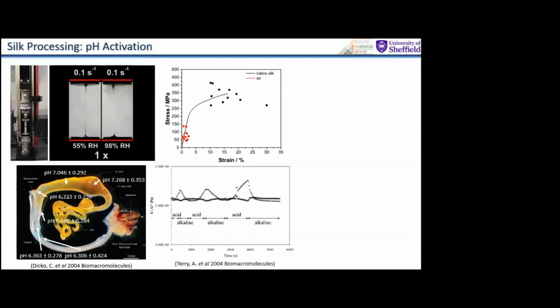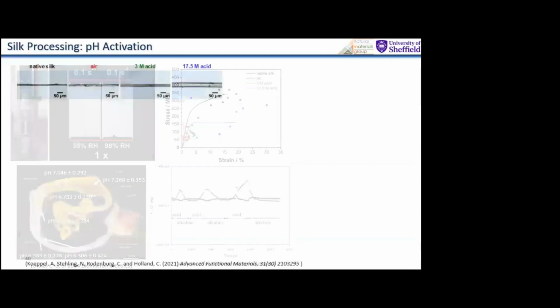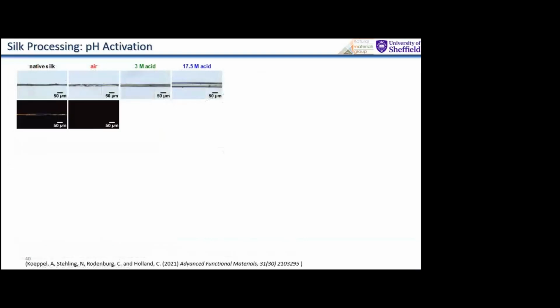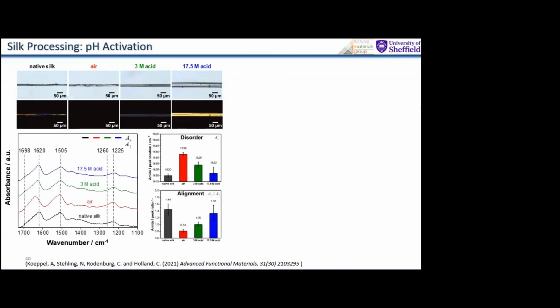So that's what we did. We wafted a little bit of acetic acid, chip vinegar, around the silk as we were pulling it into a fibre, and it made a massive difference. So this is without any acid, and then as soon as we expose it to acid, all the chains start to align, and it creates mechanical properties that are very, very similar to nature.